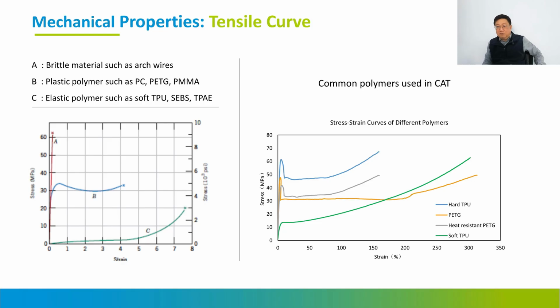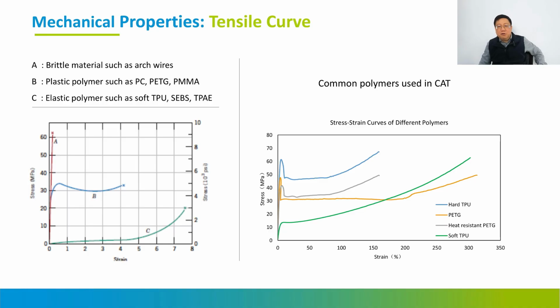However, because it's very soft, it has very low orthodontic force, so it needs to be combined with a very stiff material such as hard TPU or copolyester. So in the market, because of patent infringement issues, some liner producers or dental sheet producers will use a three-layer structure with hard, soft, hard, or soft, hard, soft. Most of the material is made of polyurethane. So the hard material can be outside or in the middle. They can have this kind of balanced properties.